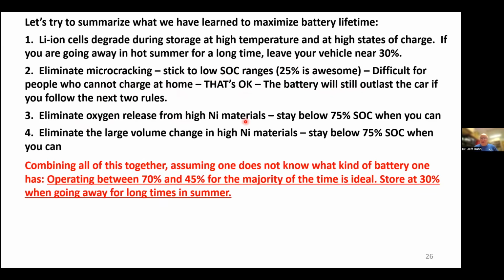Eliminate oxygen release from high nickel materials. Stay below 75% state of charge when you can. And eliminate the large volume changes to eliminate microcracking if you have a non-single crystal material. Again, stay below 75% state of charge when you can. So if you combine all this together, and assuming you don't have any idea what kind of battery you have, if you operate between 70 and 45% for the majority of the time, that's ideal. Store at 30% when you're going away for long times in the summer.